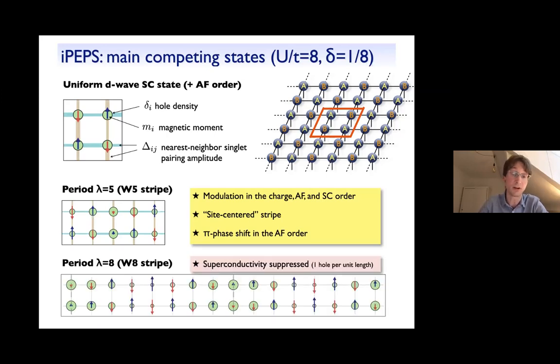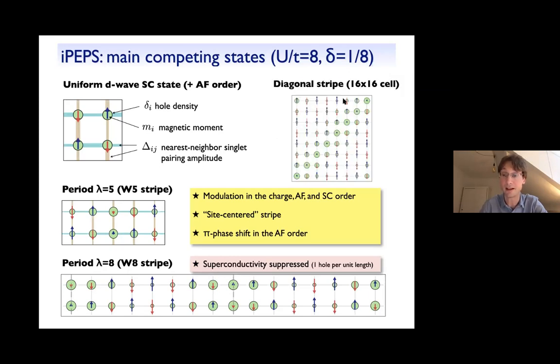Here's another example of a period 8 stripe. What's special about the period 8 stripe is that it has exactly 1 hole per unit length, so exactly a filling of 1 hole per unit length. And in this case, we found that superconductivity is entirely suppressed. There are other low energy states like this diagonal stripe as shown here. So in the end, what we need to do is to systematically compare the variational energies of all these competing states to find out which of those is really the true ground state.